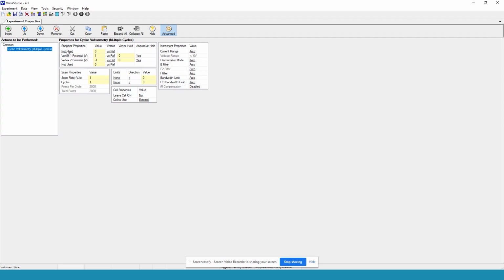So again, we will start the experiment from 0 volts versus OCP, which basically means that we start from an equilibrium position where no current is expected to flow yet. And we will use the formal potential that we calculated in one of the earlier questions as the midpoint of our scan. So in our case, the formal potential was calculated to be 500 millivolts. So for the lower limit, we will take 500 minus 200 millivolts.